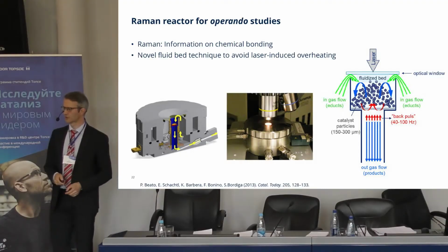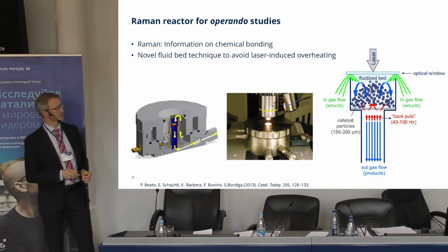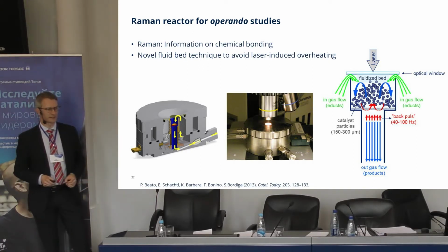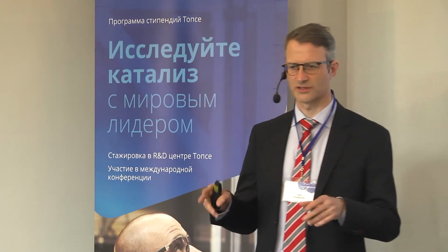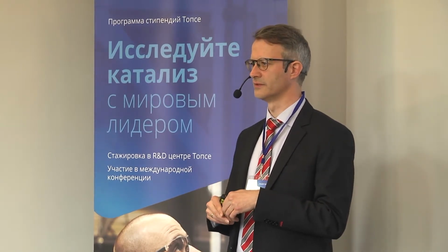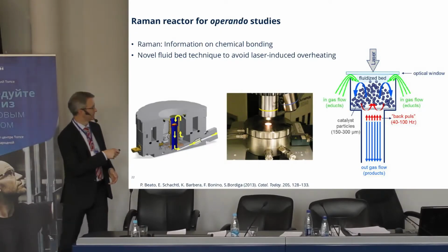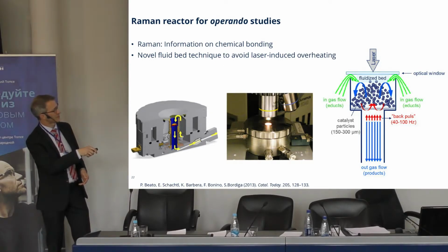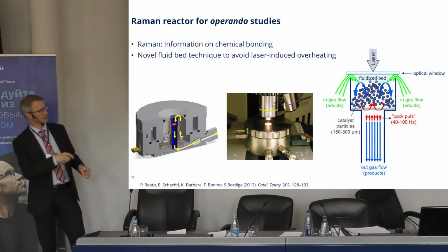In the Raman spectroscopy, we're using a special fluid bed cell, and this is to avoid laser-induced overheating. Raman tells about the chemical bonding in the sample, and it uses a high-power laser, so that will heat up the particles you're looking at, and you may get some very wrong results when you interpret. But here we have a fluid bed in this reactor, so the catalyst crushed down to maybe 200 micron particles will move around, and in this way it will be isothermal and the temperature will be well known.